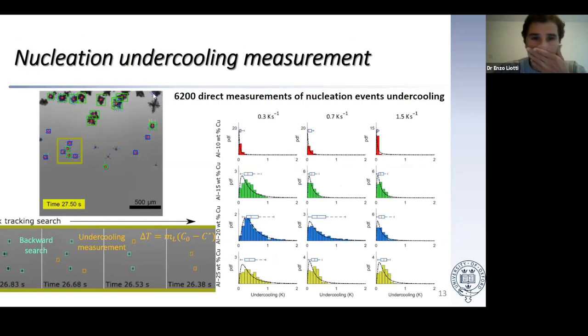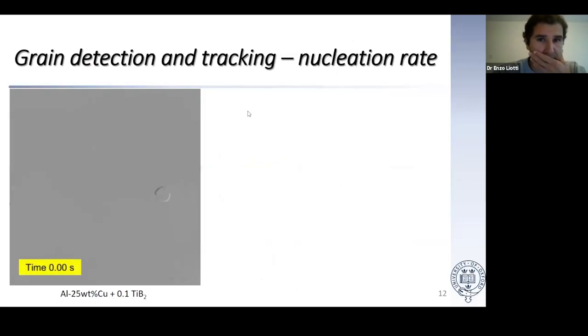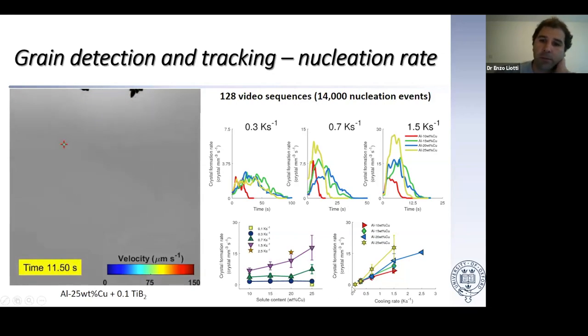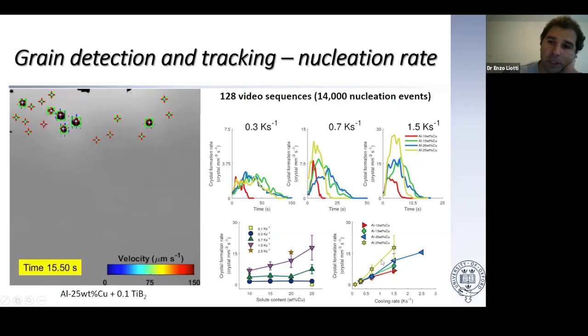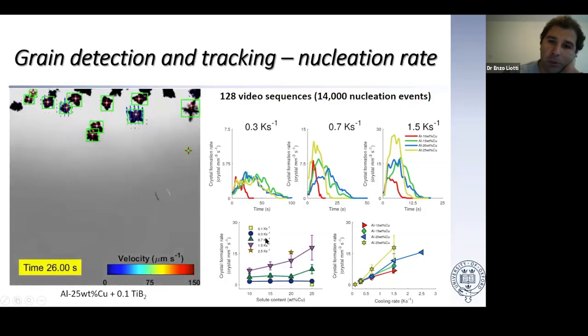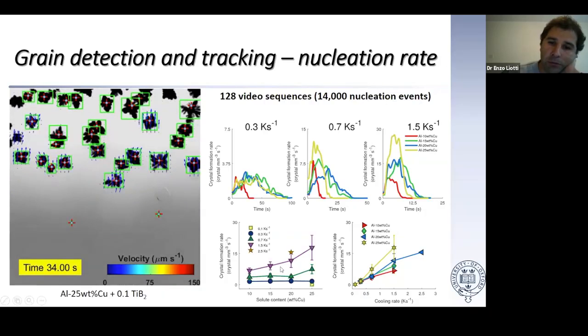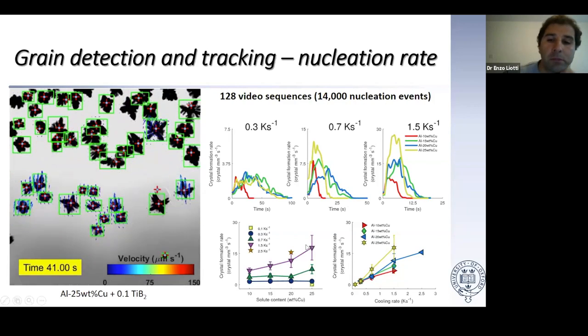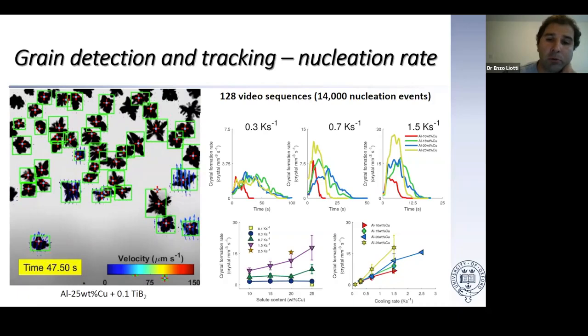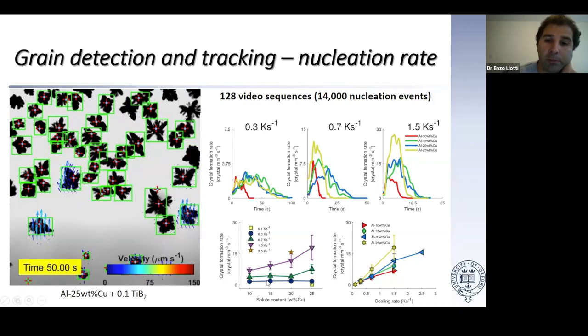That's what we observe in our data as well, and it would be concerning if it wasn't. As these data show, when you increase the cooling rate, the crystal formation rate increases. That's expected. The correlation is that when you start to vary the solute content as well, the effect of solute content is correlated to which cooling rate you're using. In other words, when you are cooling very slowly, increasing your solute content doesn't really affect the crystal formation rate, while when you increase the cooling rate, the effect of solute is more evident.